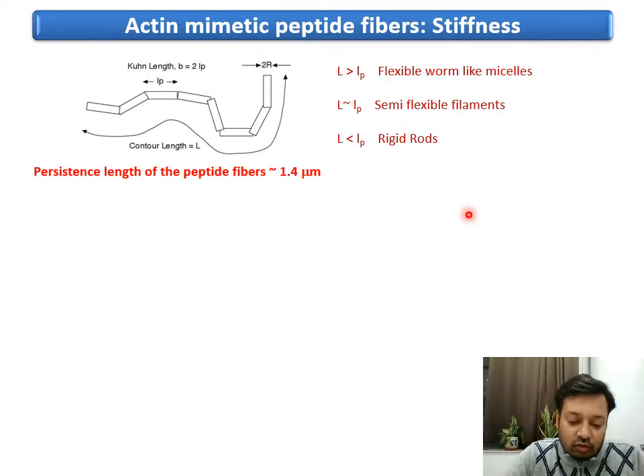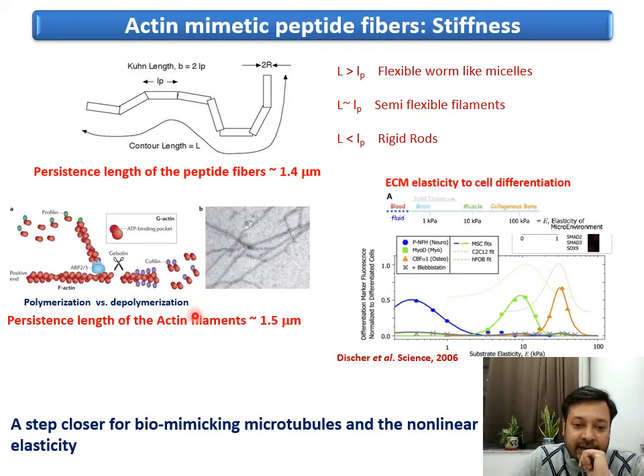Now, what I wanted to just say is that all these peptide fibers, we have checked their persistence length to find out the stiffness, because persistence length is a measure of whether it can be called a semi-flexible filament or a rigid rod, and that matches pretty well with the actin filament. And that's when we thought that if it is matching with the actin filament, this is actually closer to mimicking some of these microtubules. And can we really have a nonlinear elasticity just like microtubules for our system as well?